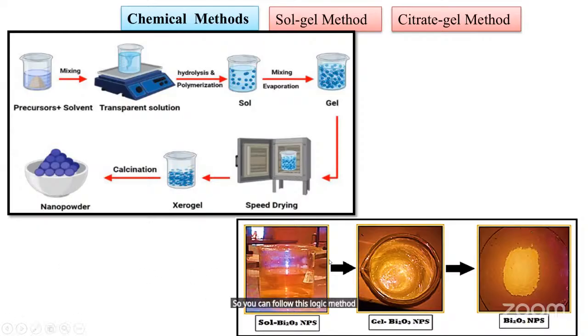This is actually the image from my research paper. I have synthesized the bismuth oxide by this method. So this is sol and this is gel, and this is yellow color bismuth oxide material. So you can synthesize plenty of materials by the sol gel method. The citric acid can be used as a stabilizing agent for the materials.